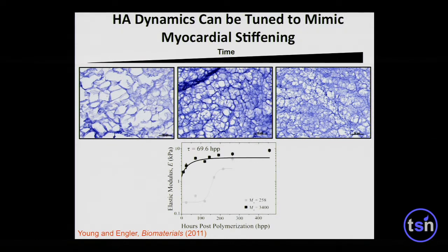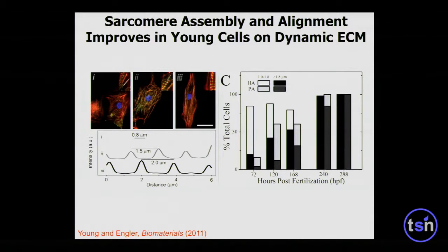So those are two ways that you can change either the starting modulus, or stiffness, if you will, for the material: by changing the bulk properties, or by changing the molecular weight of that spacing arm, which tunes the dynamics. So the longer the arm, the faster the cross-linking. And this is going to be a process that's ongoing in your culture due to a Michael-type addition reaction.